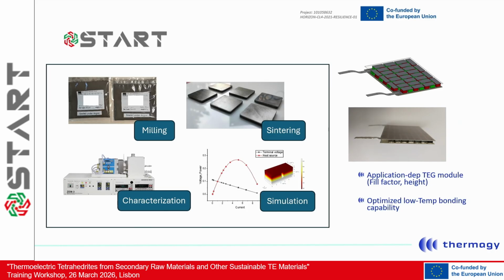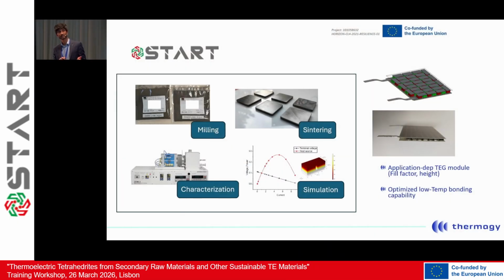We have gone through this chain now, and it took quite a long time, two to three years, to figure out the milling properties which would be suitable and the sintering set points needed. As Patricia was saying, the sintering temperature as well as the pressures that we would need. Now we have a steady supply of material coming in from Genicore soon. Then we carried out an entire characterization exercise to see what the module sizes for the pellets should be to get to a suitable power.